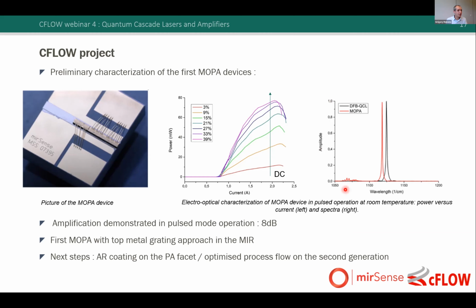You can see on the spectrum of the device that some Fabry-Perot modes are remaining. So for the next step of the characterization of these devices, we will use an anti-reflection coating on the emitting facet of the PA section in order to suppress these Fabry-Perot modes and to have a single mode emitter. And we will also use this optimized process flow for the second generation of MOPA devices in order to increase the value of the amplification we have achieved so far.